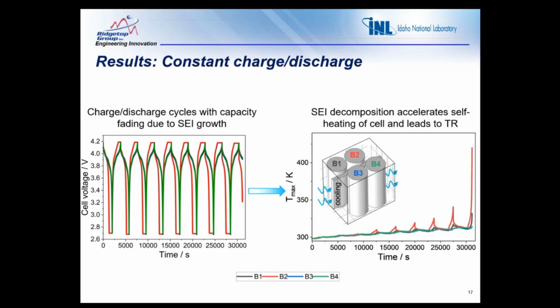This relationship indicates that as the temperature increases, the rate of the decomposition rises exponentially, and also it raises the rate of the heat release term, further fueling the rise in temperature. And eventually, this cycle of self-heating leads to thermal runaway, a catastrophic failure mode for batteries. The inset image illustrates the arrangement of cells B1, B2, B3, B4 in the module.